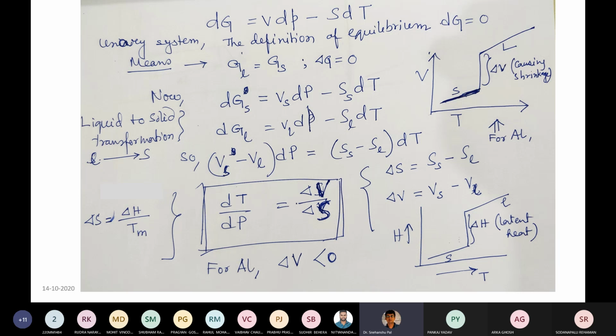Now, if you check, dGs equals Vs dP minus Ss dT, and dGl equals Vl dP minus Sl dT. Now, if liquid to solid transformation is occurring, what happens with the volume term? In the case of aluminum, there is a shrinkage. When liquid aluminum becomes solid aluminum, there is a volume shrinkage.